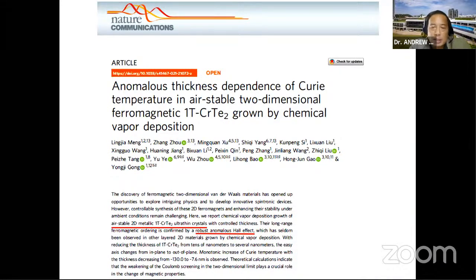So they used electro method to show the magnetism. And they also showed that there is an increase in Curie temperature as the thickness decreases from 130 nanometers to 7.6 nanometers. So they didn't really reach monolayer. Well, it's near monolayer, but it's not monolayer. It's few layers, 7.6 nanometers.